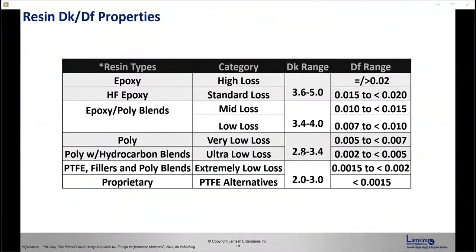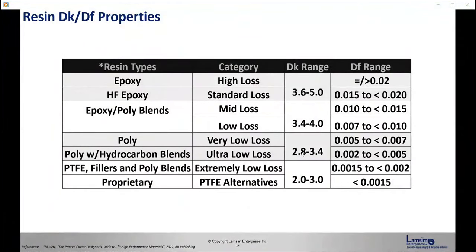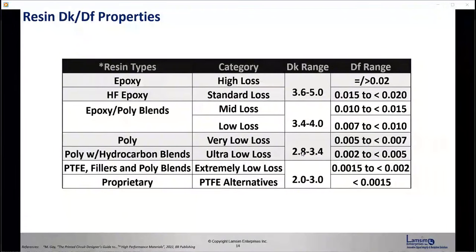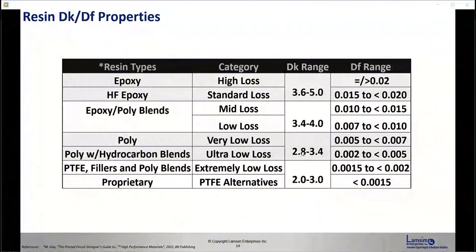Here's an example of DK/DF resin properties. Twenty years ago, this list was shorter — mostly epoxy-based, with higher loss materials and DK range between 3.6 and 5, and DF range around 0.015 to 0.02. Fast forward to today, we have all the way up to proprietary blends where DKs have been lowered down to 2 to 3, and the DF is an order of magnitude smaller.